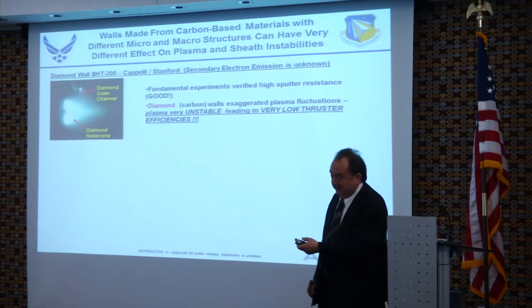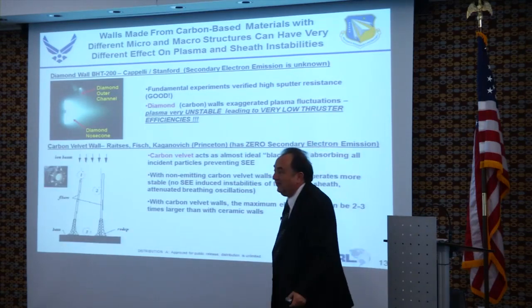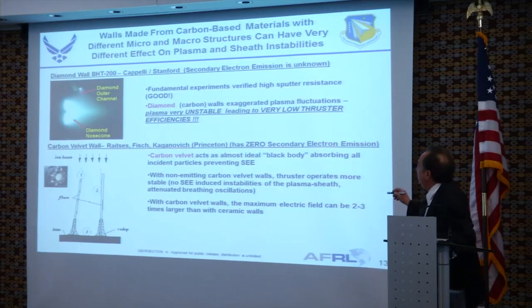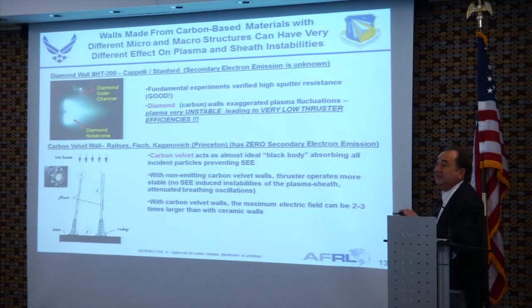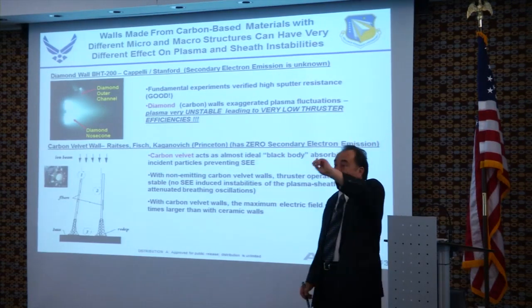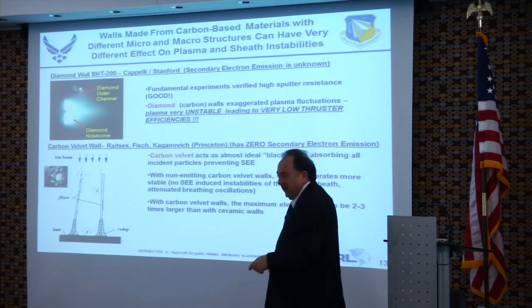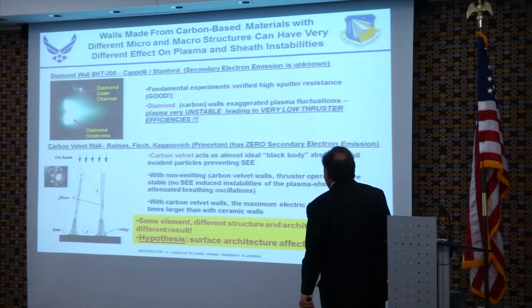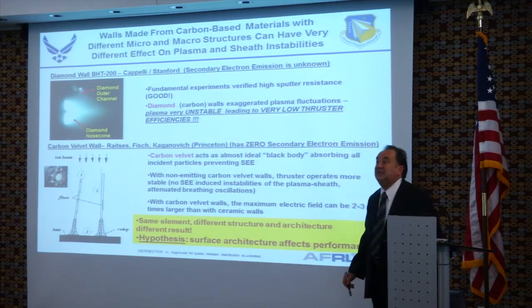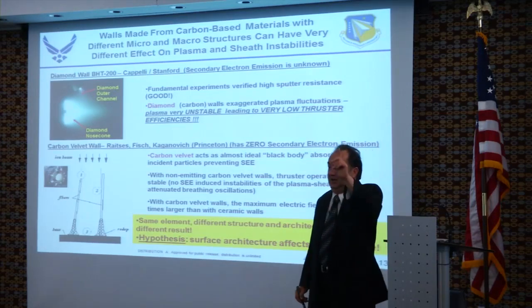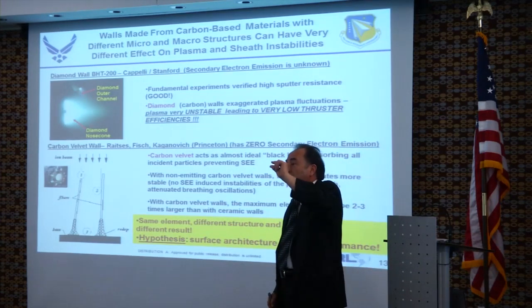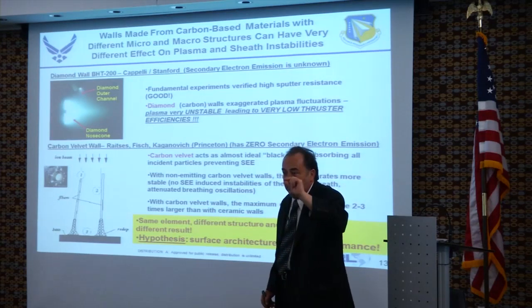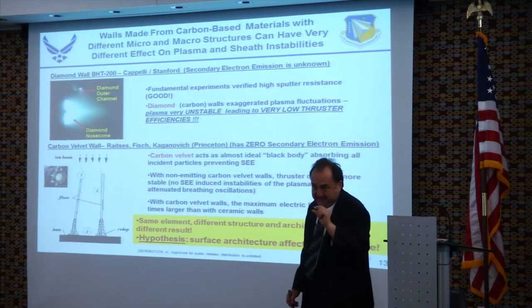Then later on is the same element, but in a different form, the carbon velvet wall, which has been used in other places too. When they used that, SEE, secondary electron emission, completely disappeared. In fact, most of the plasma sheath instabilities disappeared, which obviously they are related to. They also attenuated some of the breathing oscillations. So there's a coupling over there we don't know. Okay? So it is the same element, different structure, architecture, and you can get a different result. That's what Ahmed Ghanim's group is looking at, not only looking for the material itself, they are looking for the architecture of the surface. That's a very important thing.